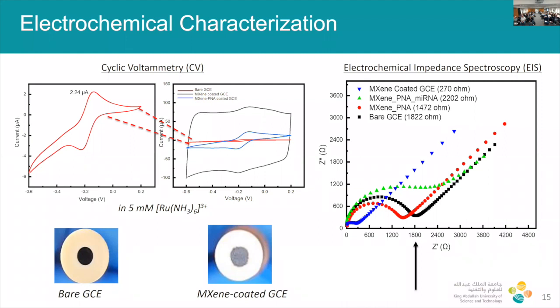Now, if you put the MXene on the surface, look how far it goes. The charge transfer resistance goes down to 270 ohms. You're getting almost no resistance whatsoever. Electrons and electron transfer go directly through to the electrodes. If there's PNA on the surface, it's going to hinder this electron transport, and you see the radius go back up. And now, if you hybridize the microRNA onto the PNA, now you have a much bulkier duplex, right? And that's going to hinder diffusion further, you see the radius go up. Good. So we know we have PNA. We know microRNA is maybe somehow hybridizing and blocking the surface.